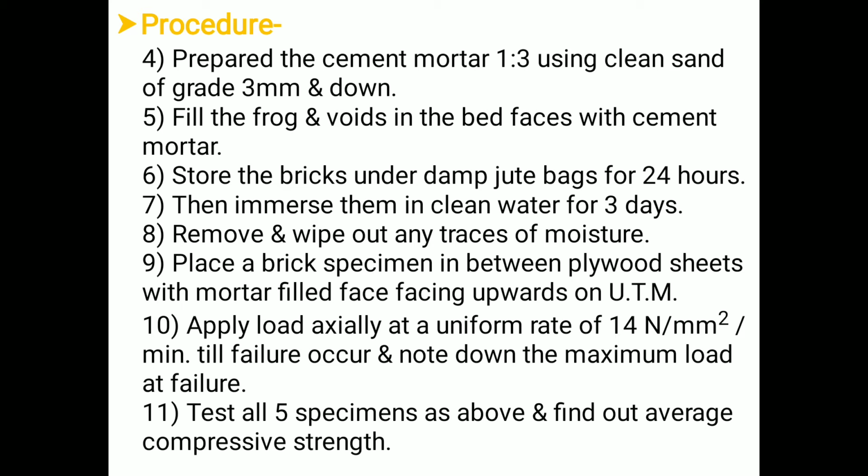After filling the frog, we have to store the bricks under damp jute bags for 24 hours. After that, again we have to immerse them in clean water for 3 days. After 3 days, remove the bricks again and wipe out any traces of moisture.